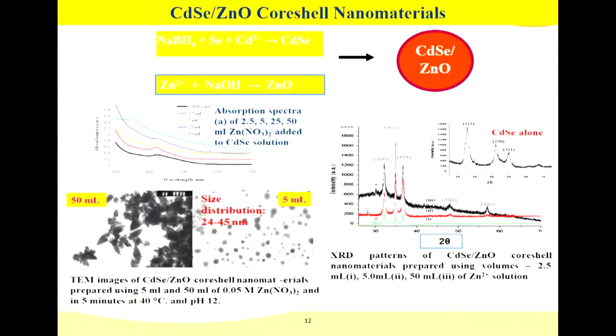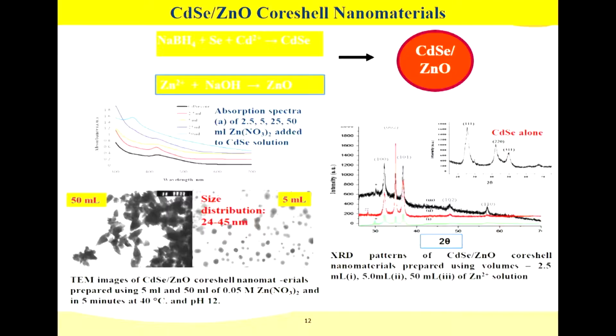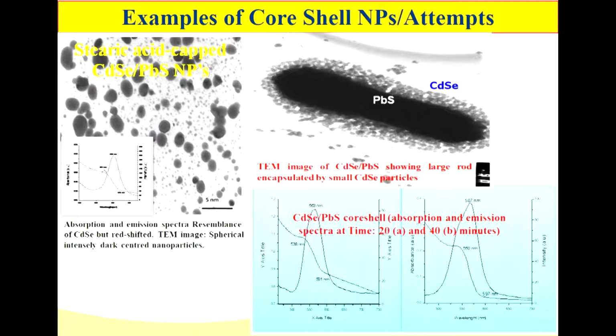at about 5 mils and 10 mils, that's when you end up with your spherical nanoparticles that are rather darker on the inside, showing that indeed on the surface and the inside are not the same, which are characteristics of core shell structures. But as you increase the amount of zinc oxide, you end up with high amount of zinc oxide particles that you can see here from a structure that shows very crystal-like structures which are typical of zinc oxide. But on the contrary, when you're adding